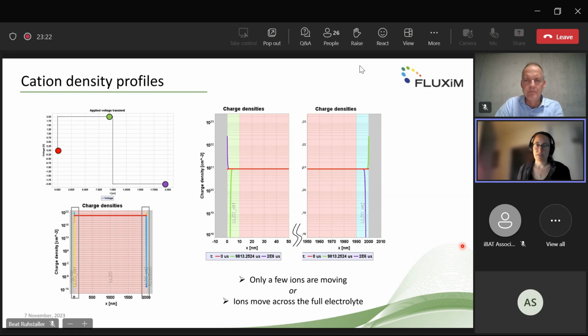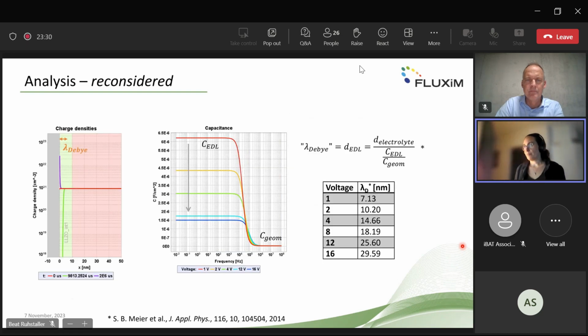Or in other words, you can also say that every ion just moved a little bit, but did not cross the full device. So if we now reconsider this in the analysis, it makes sense that we should not use the device thickness, because the ions do not travel the full device. So what we used instead, or what we tried, is to use something like this Debye length, or the accumulation thickness. And here is something we got from a related field, where the electric double layer thickness, as they call it here, can be calculated from the capacitance frequency plot at different offset voltages.